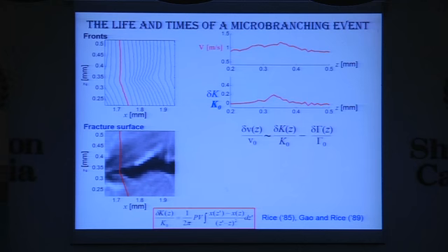So this is a static kernel that gives us the relative change of the stress intensity factor at each point along the fracture surface. Now our equation of motion equates the change in velocity to the change in the stress intensity factor and the change in the fracture energy. Every time we get a branching event, we change the fracture energy. When this branches, instead of a single crack, we have two cracks, so this contributes. Once a branch dies, the only thing contributing to the velocity is basically this line tension given by the change in the stress intensity factor.